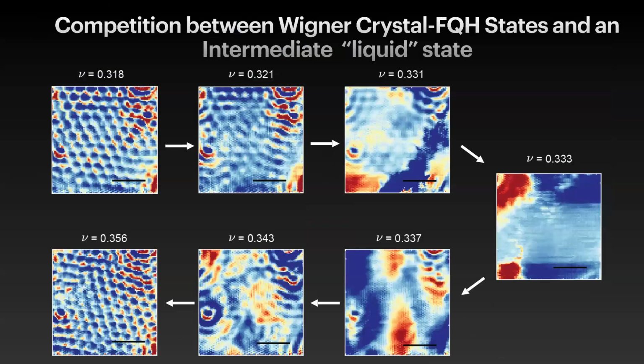As I mentioned, the process of the melting of this Wigner crystal as you go through the filling can be seen in the data. So here is 1/3. As you go towards this 1/3, you see that the Wigner crystal melts. It re-emerges at higher filling, and then it goes away again. So there are a lot of interesting things in the data.